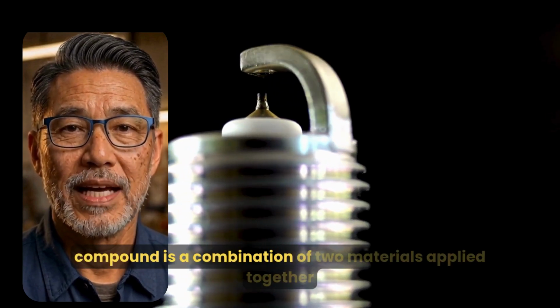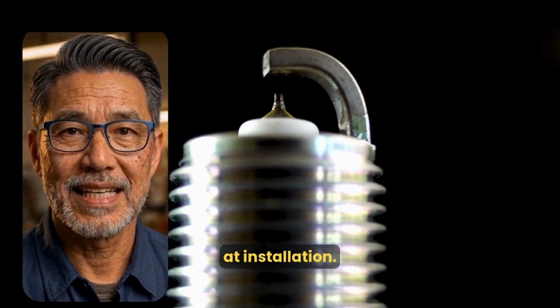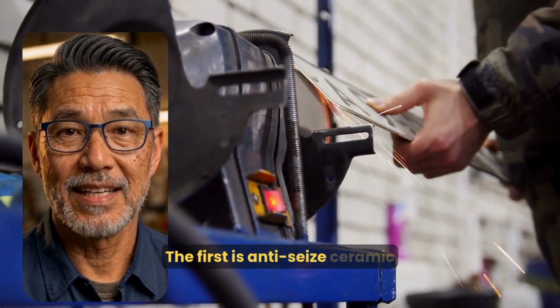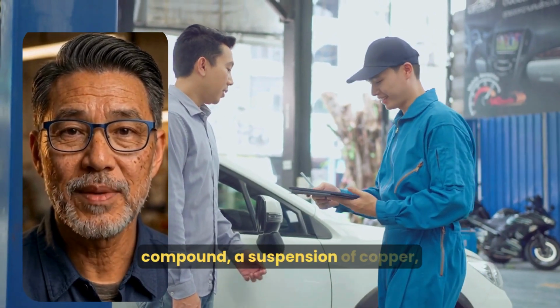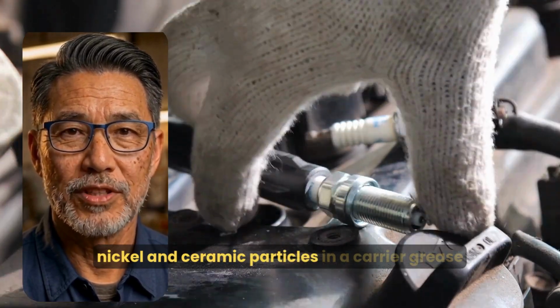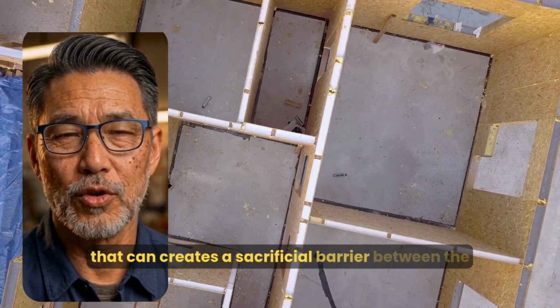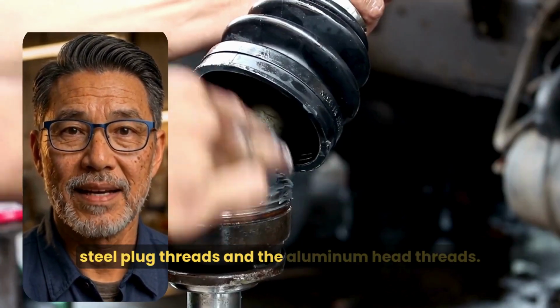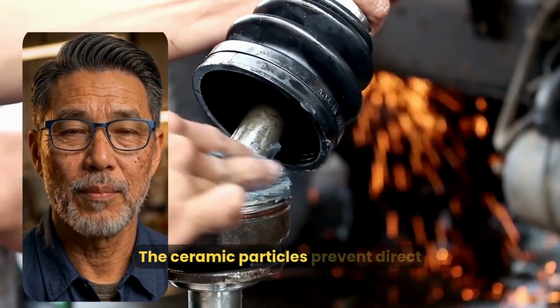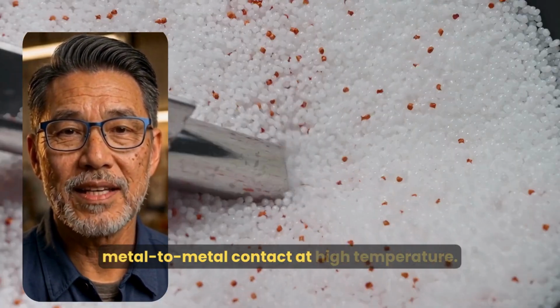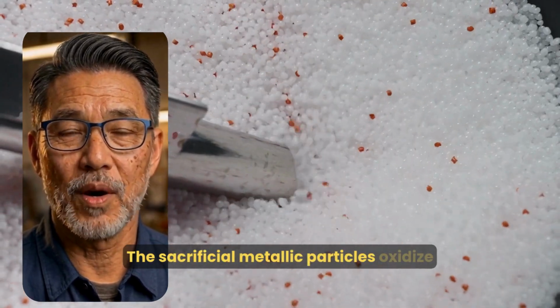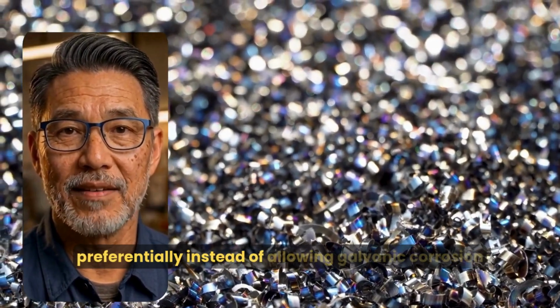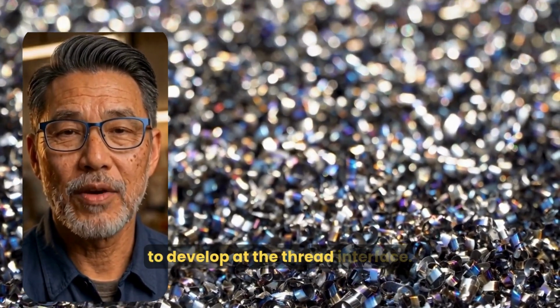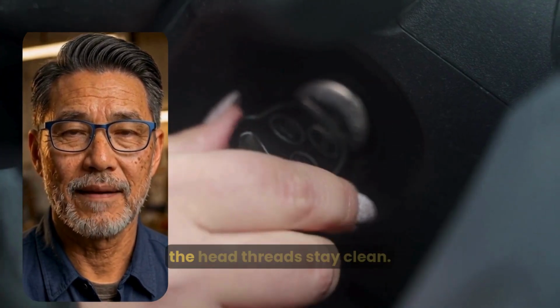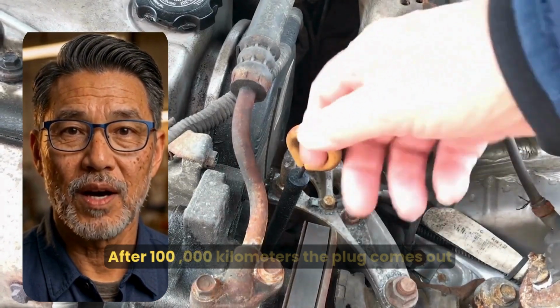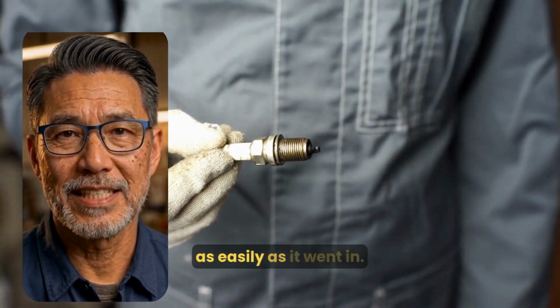The compound is a combination of two materials applied together at installation. The first is anti-seize ceramic compound, a suspension of copper, nickel, and ceramic particles in a carrier grease that creates a sacrificial barrier between the steel plug threads and the aluminum head threads. The ceramic particles prevent direct metal-to-metal contact at high temperature. The sacrificial metallic particles oxidize preferentially instead of allowing galvanic corrosion to develop at the thread interface. The plug threads stay clean, the head threads stay clean. After 100,000 kilometers, the plug comes out as easily as it went in.